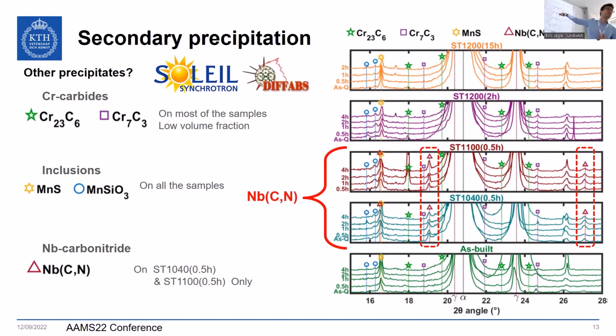So they are precipitates at high temperature, but at too high a temperature, 1200, they are dissolving. So then we cannot see them anymore. And after aging, they do not reprecipitate. It's not a high enough temperature.